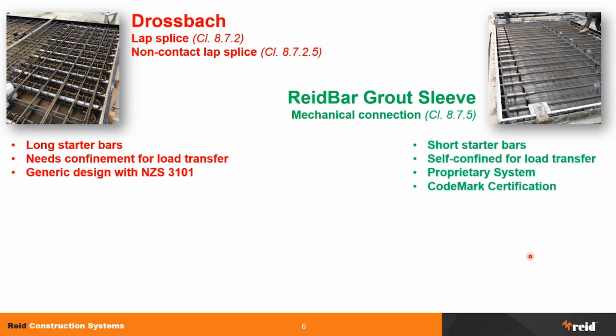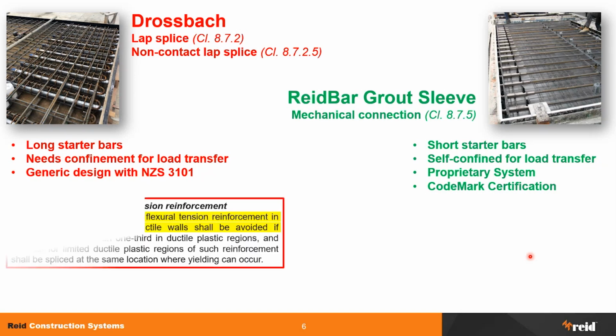For ReidBar Grout Sleeve, we have much shorter starter bars, and the system is self-confined for the load transfer. It's tested like a coupler in free air, so it doesn't need the concrete to transfer the load between the two bars. Although confinement is still a good thing to prevent spalling and cracking, the load transfer is ensured regardless. And it's a proprietary system, and it's covered by CodeMark certification, as we mentioned before.